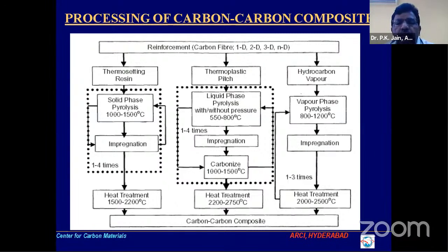To make it a high temperature material, it has to be carbonized, and once you carbonize it, the non-carbon material of the polymer will go out. It becomes highly porous. It has to be densified, and this whole process is called impregnation cycles. This will take 1 to 4 cycles depending on the matrix you have selected. And finally, if you heat treat to 2200 degrees and above, or sometimes 2700 degrees centigrade, your matrix will also completely convert into carbon. That's why it is called the carbon composite, where the carbon fiber is reinforced in a carbon matrix.